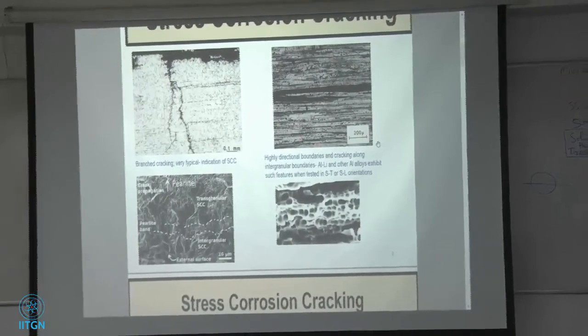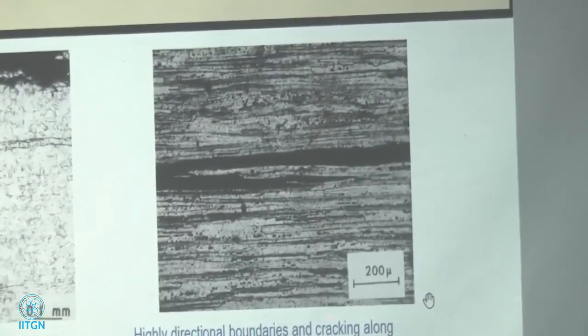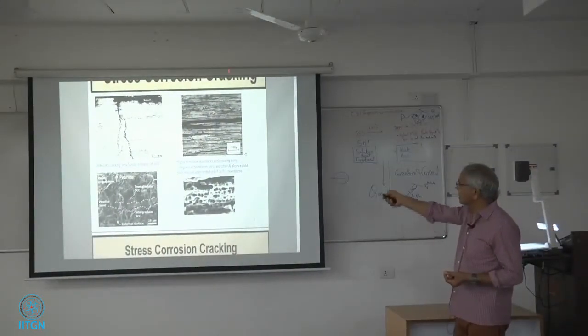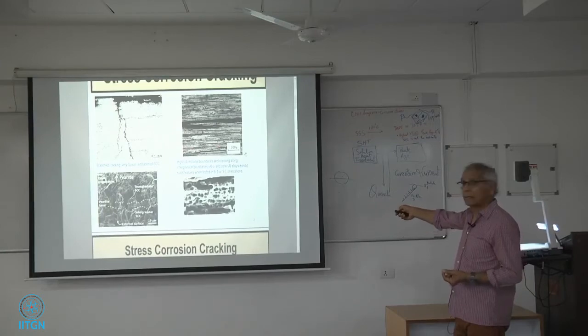Whenever you are working with materials which have got these grain boundaries like this, you have to worry about stress axis along this direction. You really have to worry about it because these grain boundaries are perpendicular to your stress. Once the crack starts, there's no way to branch out. It's going to go right along these lines. And that happens in commercial type of alloys.